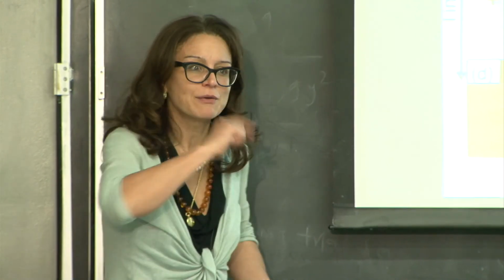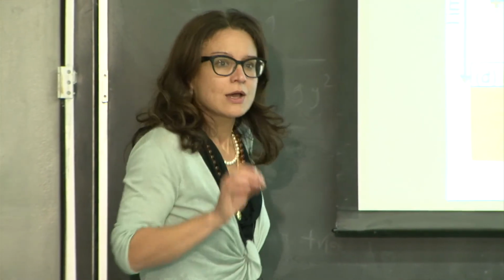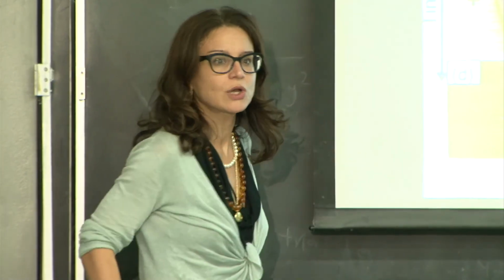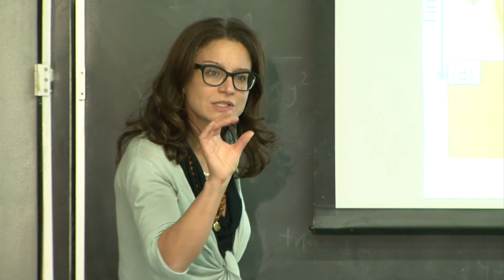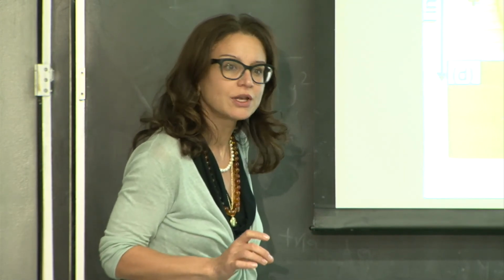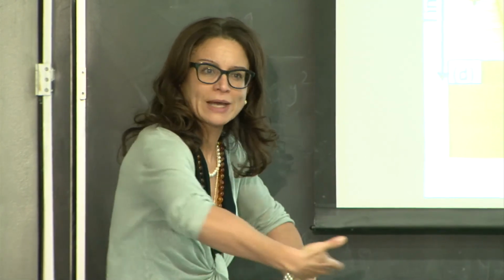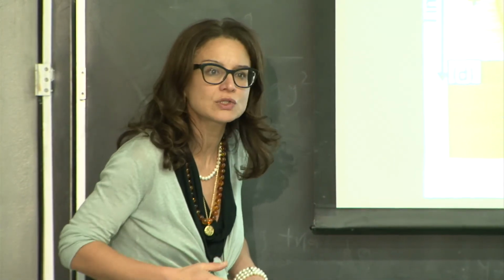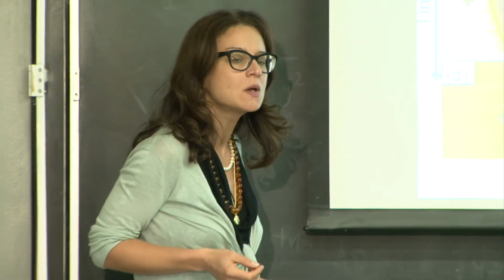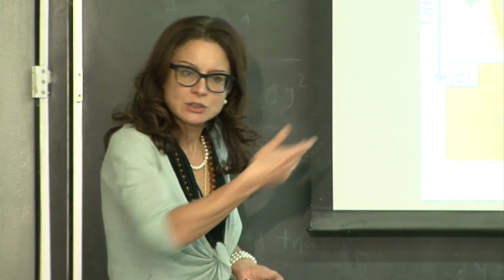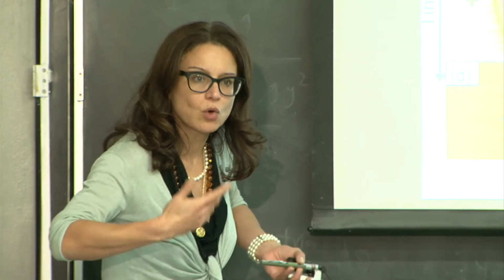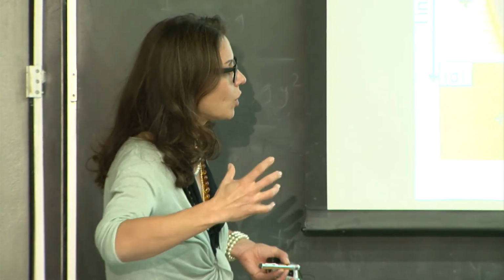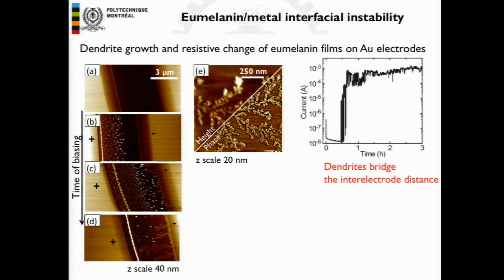And then another thing, and then I promise you that I'm done. Again, for you it's trivial. For physicists, it's a revolution. So you have water, you have salt. You want to study the fundamental properties of your natural material. So you make measurements, you pattern your substrate with metallic electrodes, typically with interelectrode distance on the micrometric scale. You are in a wet environment because it's a hydration-sensitive material, so you really want to maximize the chance to detect properly your electrical response. And then what do you do, in your opinion? If you have a natural material, spin coated on a patterned substrate in a wet atmosphere, what is going to happen?